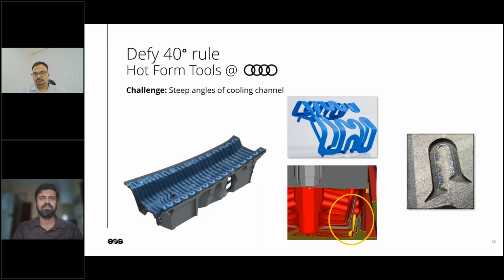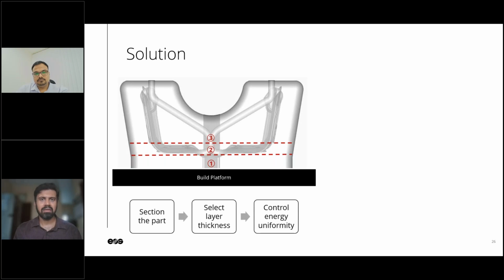And we talk in terms of 20, 40, 60 micron sizes. So even if there is some blockages there, it's going to have some issues. So we tend to avoid such burnt marks, right? So what currently the solutions that we have offered is, we section the part at first, right? We select different layer thicknesses where some layer thicknesses we can have a very high, we can run in seventh gear, basically highest productivity, probably 60 or 80 micron layer thicknesses, right?